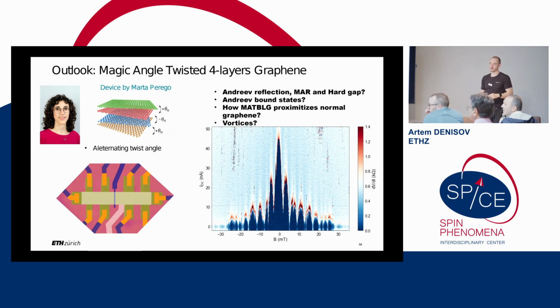And suppose you use only 3 layers? We didn't do it, but I heard that at other groups in Boston it actually is the way to go. Another advantage of 4 layers is that the more layers you put, the critical temperature goes up and the superconducting gap is bigger and bigger. There is a limit to that. Apparently at about 5 layers there is no real change, so just stick to 4. That's pretty much the maximum you can get in terms of superconducting effect and critical field.